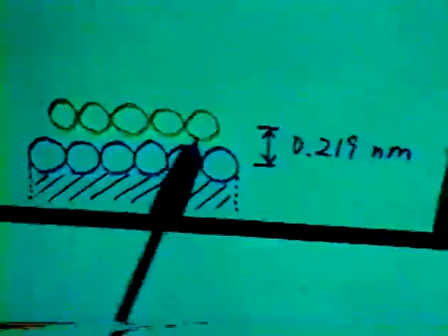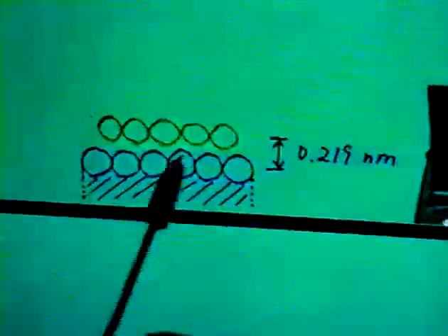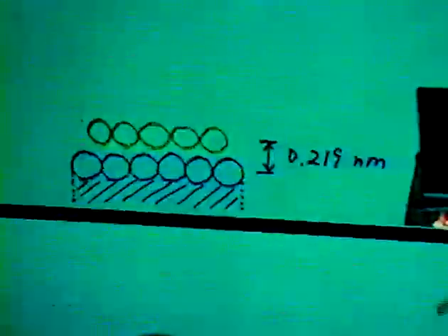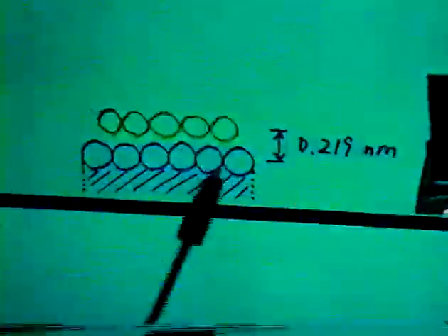The fitting is very good, showing a reliability factor of 2.7%, but still, at the points shown by arrows downward, there is deviation between the fitting curve and the experimental value. Therefore, we furthermore added a different distance of tin-ruthenium or tin-tin bonds. That is a four-way fitting.